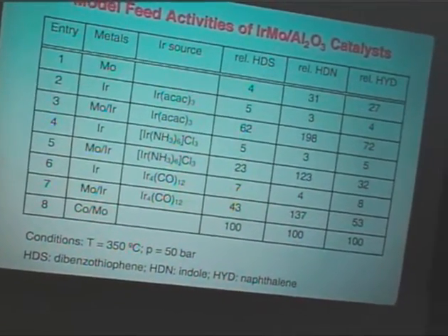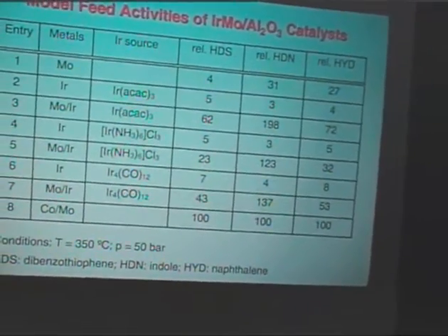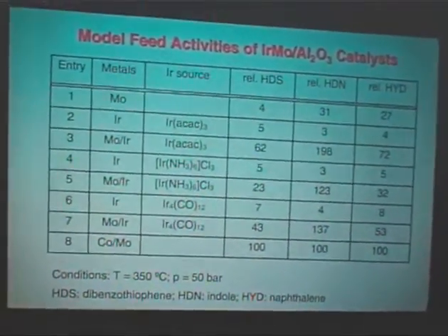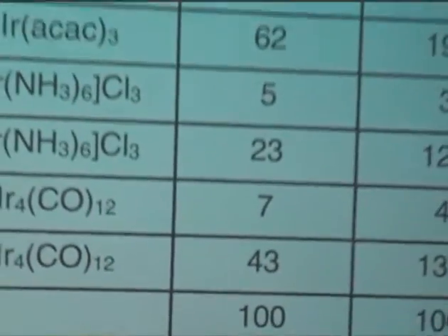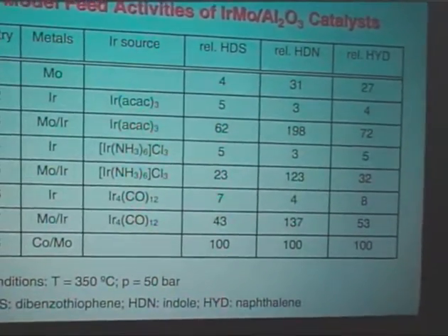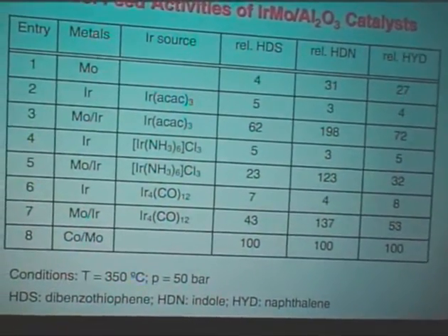With this series of catalysts, we were again running hydrotreating tests, and we observe for a pure molybdenum sulfide catalyst a very low HDS activity, but pretty good HDN and hydrogenation activities.